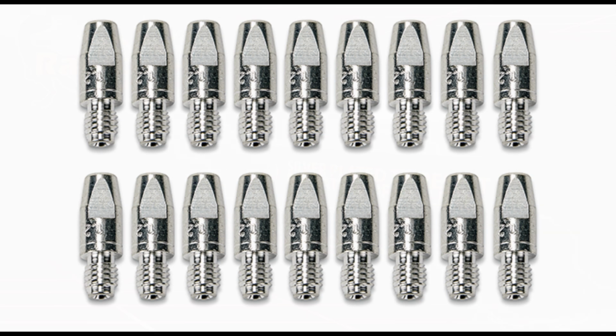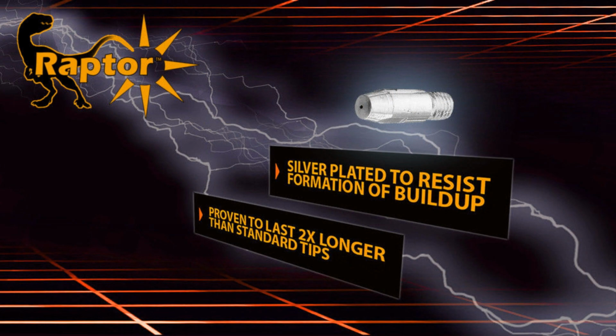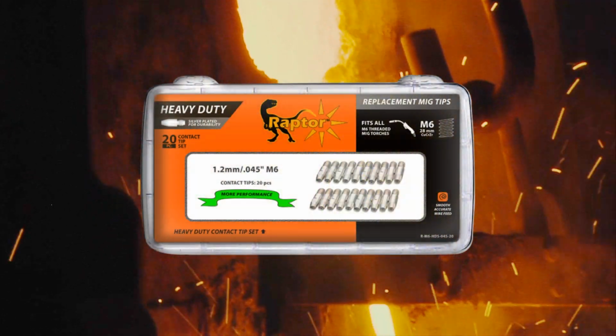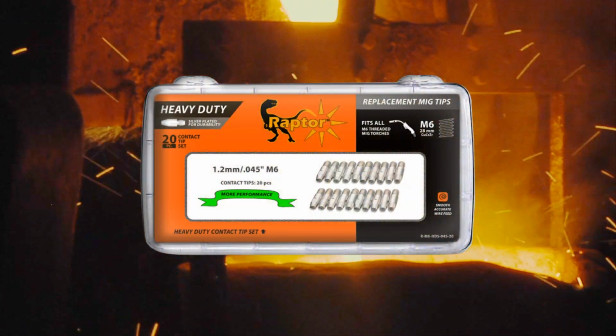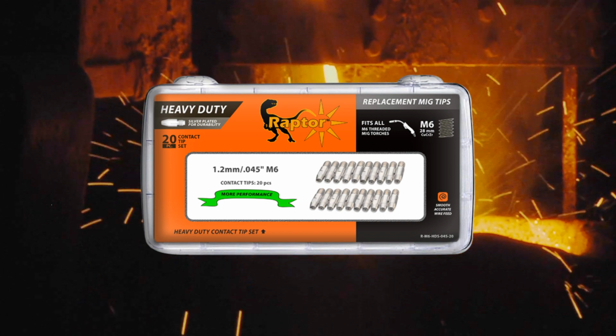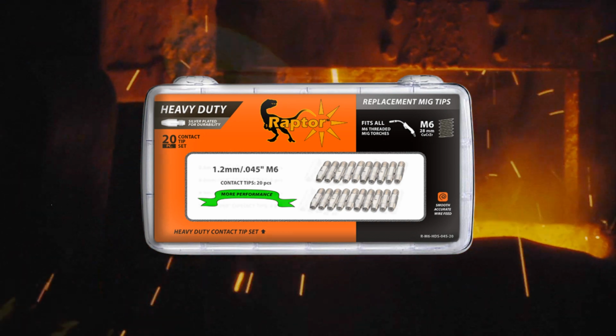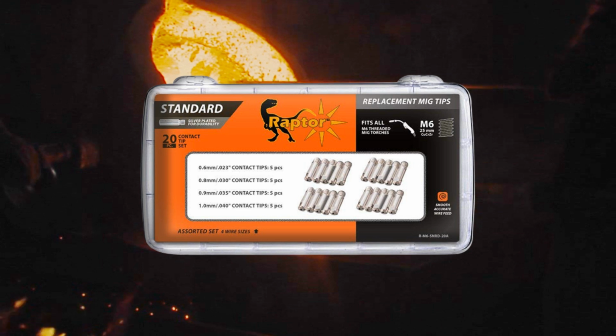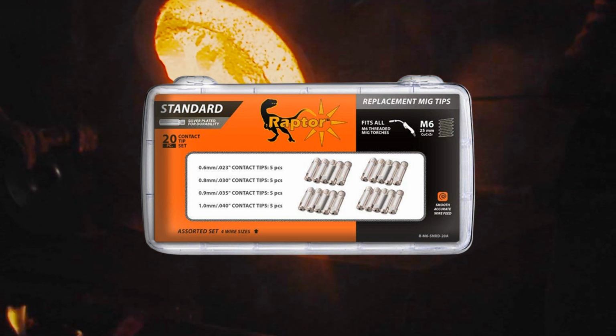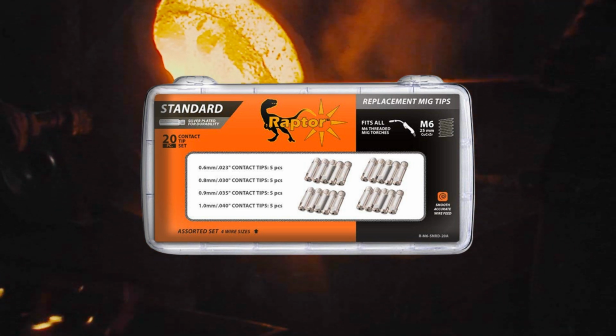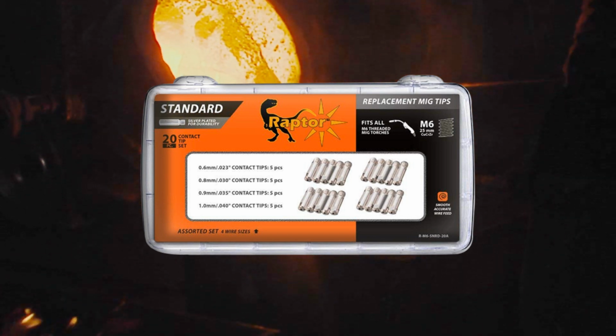When a contact tip begins to wear, the tip center hole elongates and loses electrical conductivity, which greatly affects the gun's ability to transfer current to the welding wire. With significant improvements in material, a silver-plated contact tip typically costs up to 50% more than the standard contact tip, typically a chromium zirconium non-plated contact tip. Welders who choose to use a silver-plated contact tip usually do so for one reason: to greatly reduce welding downtime.